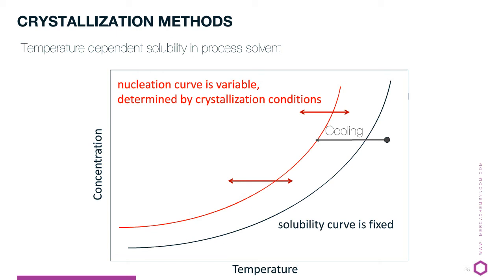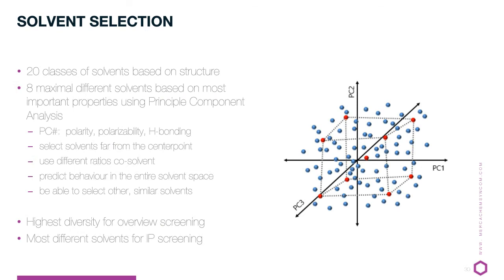Your selection of the solvent or your solvent mixture, that one determines your solubility curve. That one is fixed. But your nucleation curve, so the form you actually get by nucleation, that one is determined by your crystallization conditions. So the cooling rate, the anti-solvent addition rate, and evaporation rate.